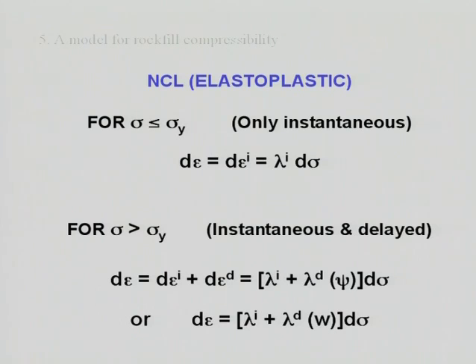I am going to build an elastoplastic model for one-dimensional conditions. For stresses smaller than this threshold value, let's simply relate the increments of strain in a linear way with the increments of stress. And when we have instantaneous and delayed deformations, then we have to add the two contributions, and we have to recognize that the delayed component depends on suction. And since both are related linearly to the stress, let's assume this very simple relationship here for the increments of deformation. The only thing we need now is to specify this equation here and to propose something for the elastic